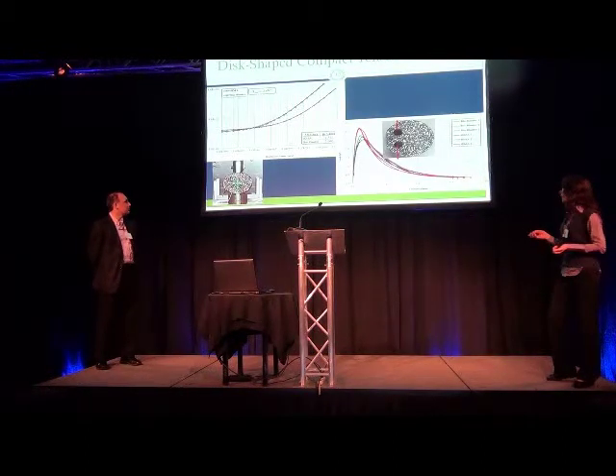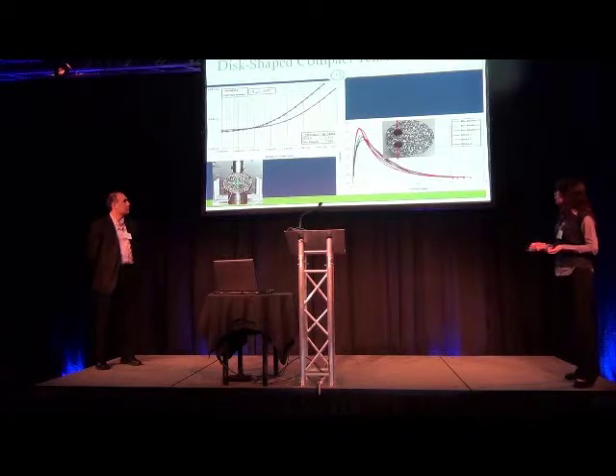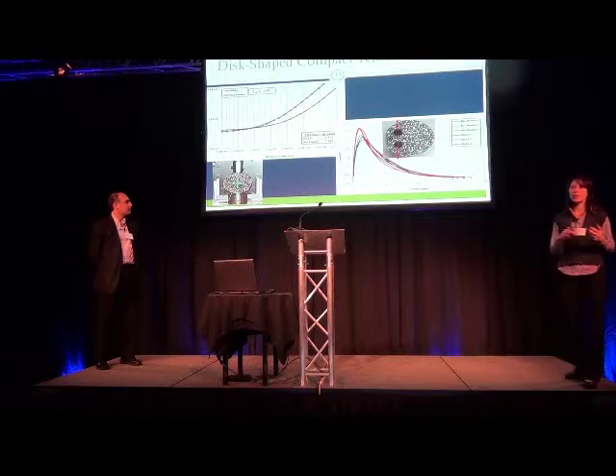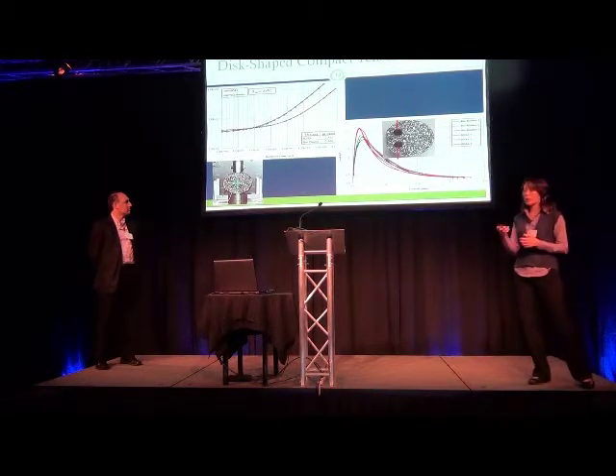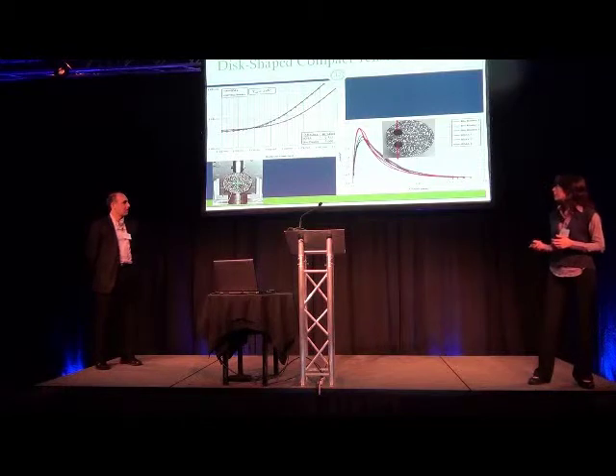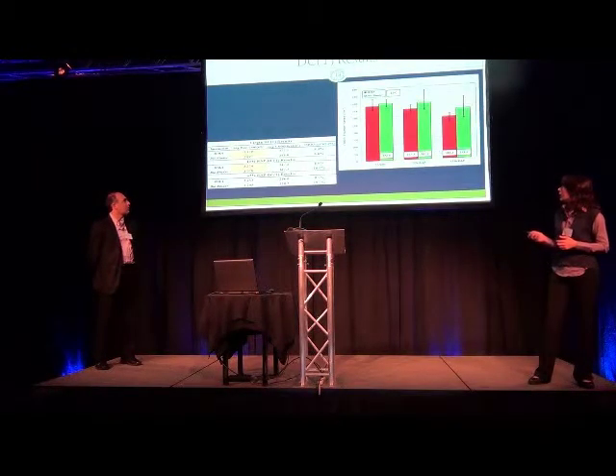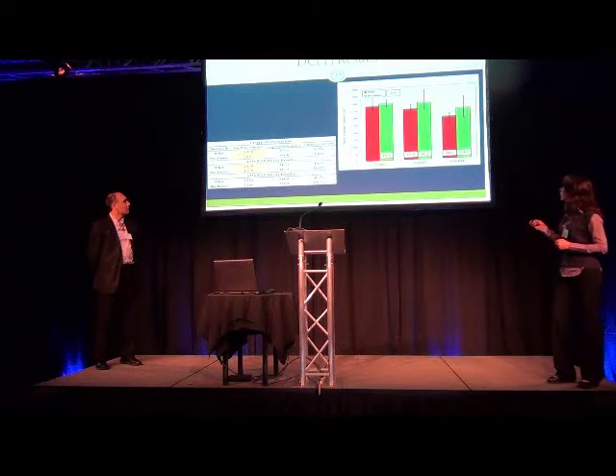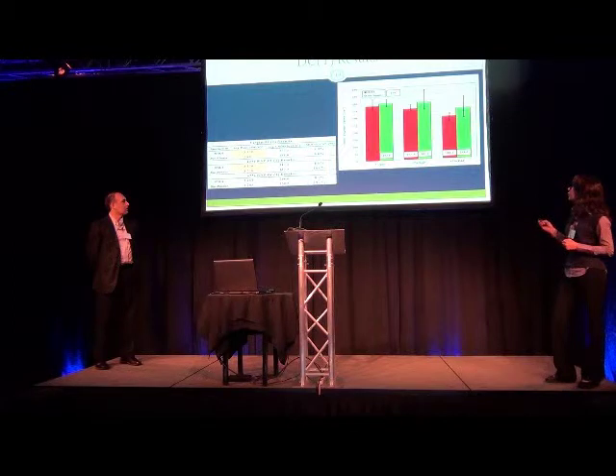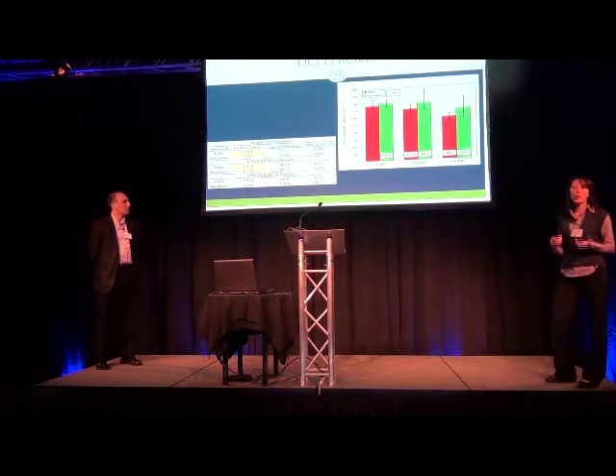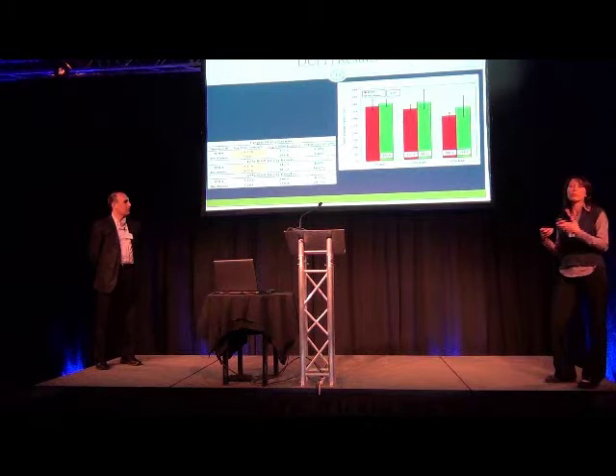We also did a lot of fracture tests and tensile characterization. This is the fracture test that we did here. We measured the fracture energy and how much energy it takes to crack this material, and the results were very promising in terms of cracking. This is the energy. You can see here the column for the virgin material, and the green is our adhesive, the red is control. And for 45% RAP, we are still much above the control one, which means it takes more energy to break the material when we have the bio-adhesive in it compared to the control one.